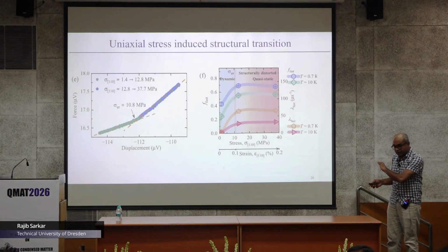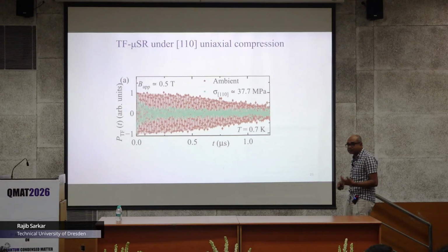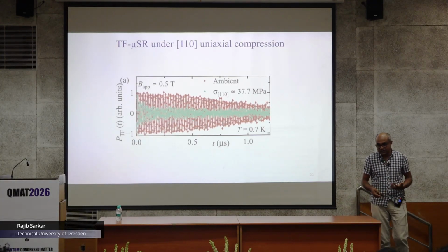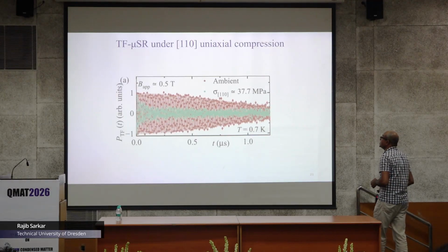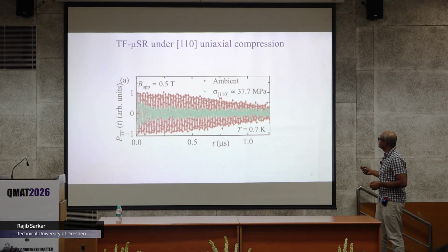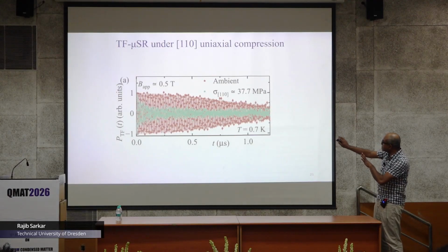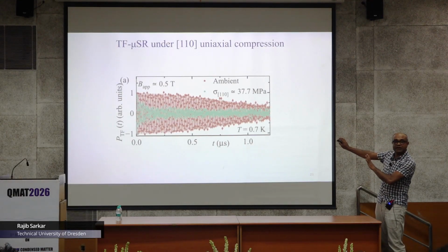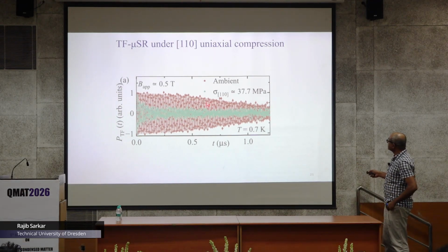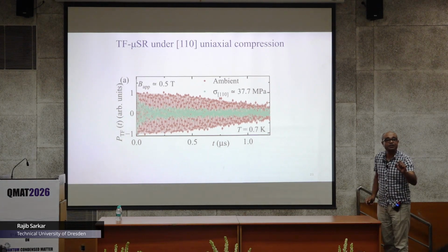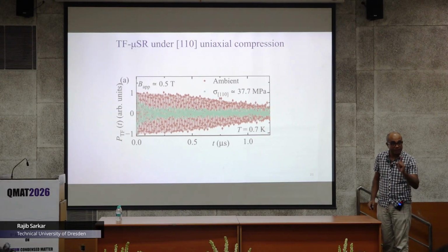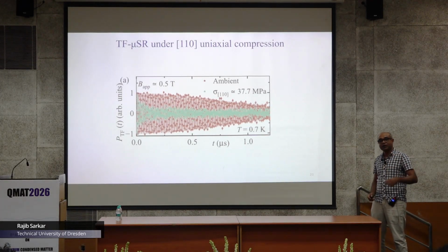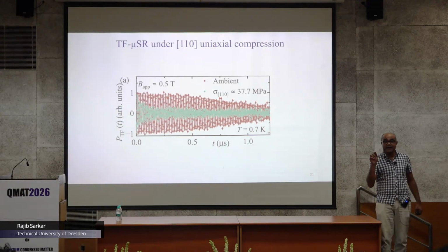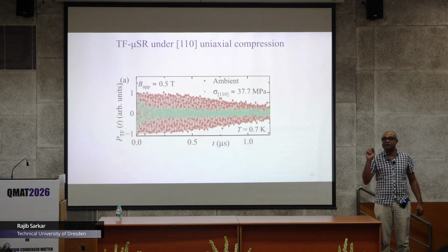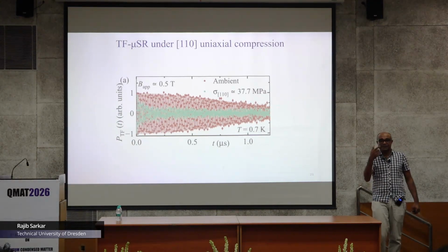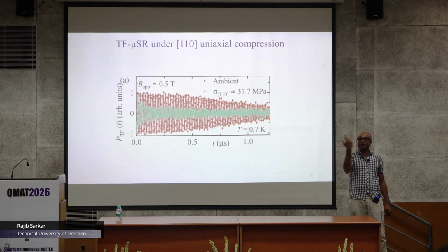So these are the first signatures we got. Of course, you can do more detailed experimental studies. For example, we have also done transverse field muSR under again 110 uniaxial compression, and that is clear cut. As an experimentalist, you immediately see the dramatic change here. This is the rate curve, the ambient pressure data at 0.5 Tesla. We apply an external field, and as Moik told, the muon has a gyromagnetic ratio of 135 megahertz per Tesla. So as soon as it senses a 0.5 Tesla field, the muon will start to precess.